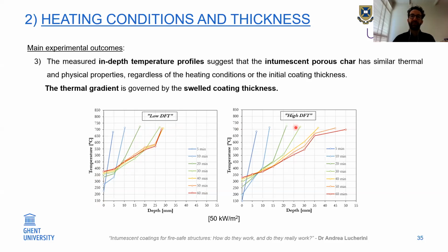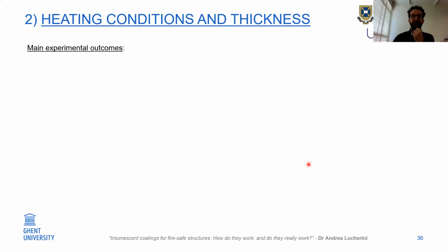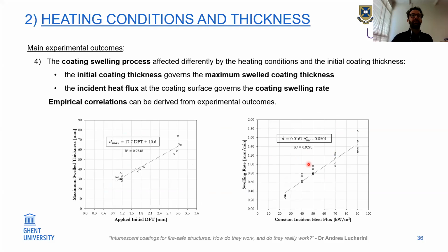But the difference is that in the case of a high DFT, the coating starts increasing temperature at the steel and the coating keeps swelling. And the temperature of the surface is a sort of constant based on the applied heat flux. So what happens is the thermal gradient is governed by the swelling coating, and mainly the gradient within the coating between the two temperatures, which is 300-350, and the temperature at the surface defined by the incident heat flux is stretched by the swelling of the intumescent coating. And another important aspect is that the coating swelling process is affected differently by the heating condition than the initial coating thickness.